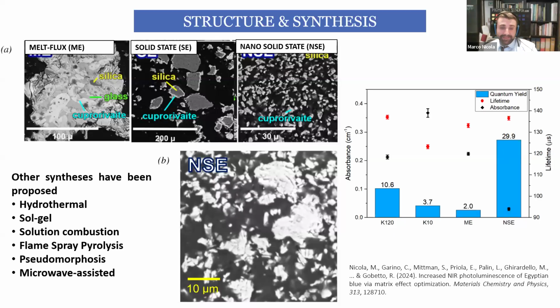And the features are different, starting with the color. The melt flux method produces Egyptian blue deeper in color. Instead, solid state produces a pale Egyptian blue. And the structure of the grain is very different, because in the flux method, you have crystals of Egyptian blue in a matrix made of copper-rich glass. Instead, in solid state, you have grains of silica surrounded by cuprorivaite, that is the main component of Egyptian blue, the one that is luminescent.